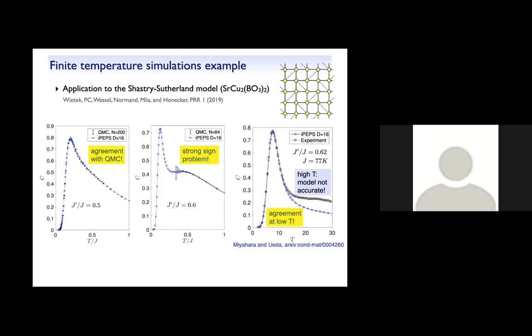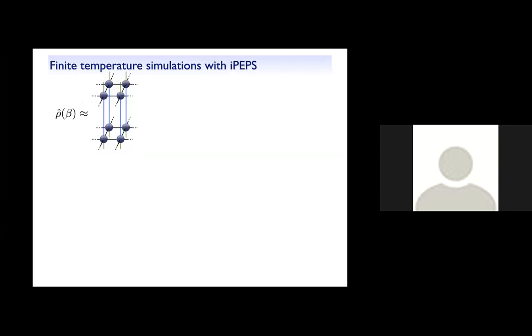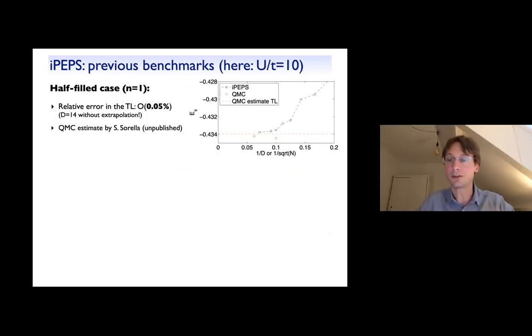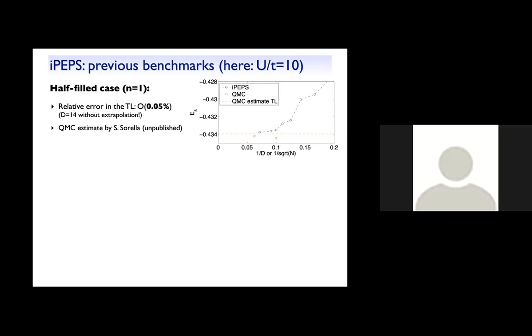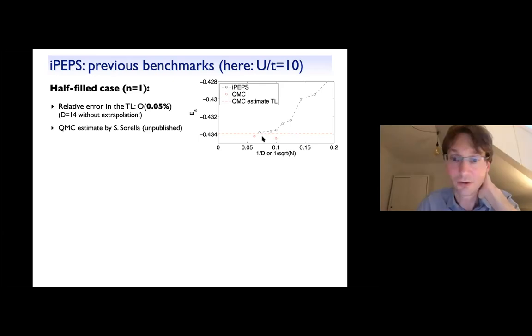I have a question about one of your very first slides, where you showed QMC simulations versus PEPS simulations, and the QMC simulations seem to give you lower bounds. Is this a coincidence, or is it systematic? Yeah, in finite size data it is often the case that you approach the energy from below. These are finite system sizes, and then you extrapolate to the thermodynamic limit. The dashed line is the extrapolated data in the thermodynamic limit, but the finite system size data comes from below. So that means the combination of iPEPS and Monte Carlo is actually giving you a much better result, because you can sandwich it between the two. Yeah, that's true.